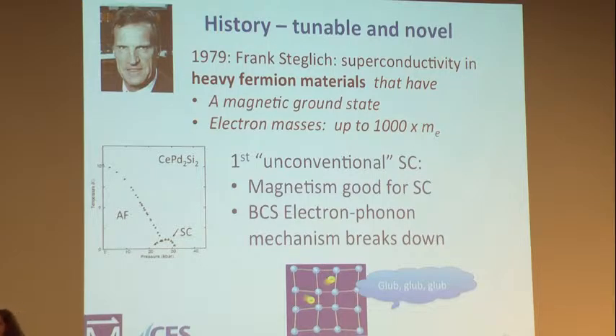Now, history. This, to me, is the beginning of unconventional superconductivity. By the way, for those of you that are experts in superconductivity, I'm being very provocative, but I stand by what I'm saying. So Frank Steglich discovered something called a heavy fermion and then a heavy fermion superconductor. And Gil Lonzarich and his group then did work on this particular one, cerium palladium 2 silicon 2. Now, why are they called heavy fermion superconductors? Because the fermions, the quasi-electrons that are carrying the current, are very heavy when they're measured thermodynamically, like using specific heat measurements. They're typically 50 to 1,000 times the electronic mass.